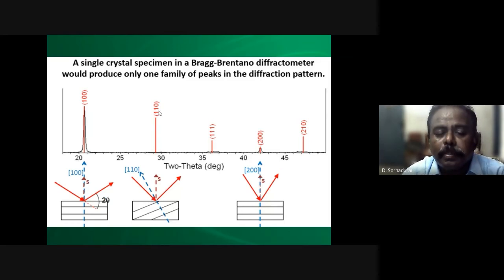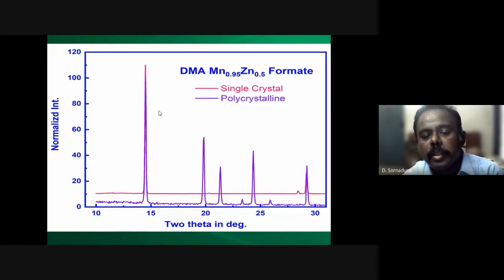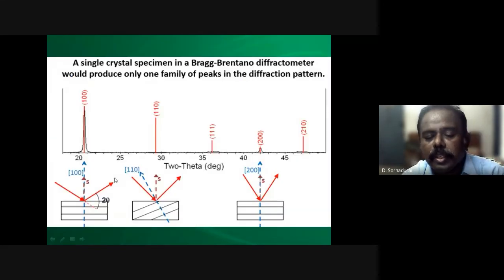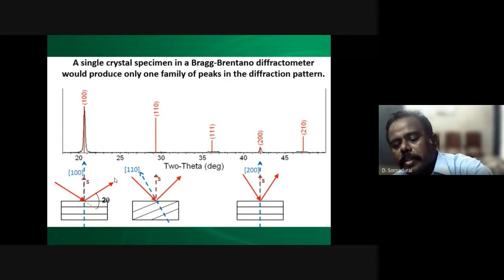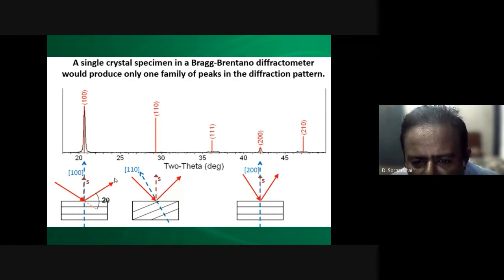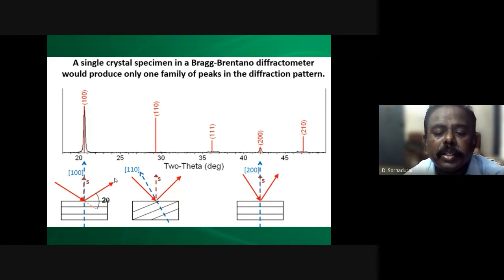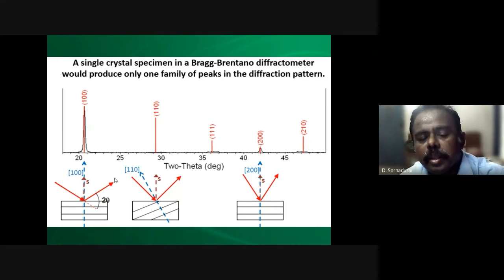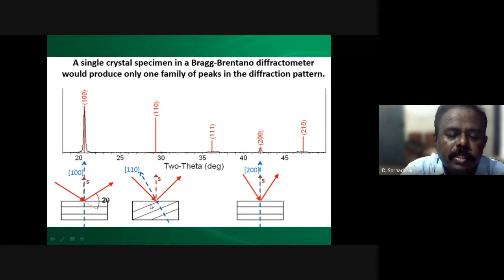As I told in the previous case, here this peak has not appeared. This peak has not appeared. Only this peak and this peak have come. The reason is they are oriented in a different direction, whereas 100 and 200 both have the same type of orientation. That is why the 100 plane is coming and the 200 plane is coming. Whereas these 110, 111, and 210 peaks are not coming at all, because the Bragg condition is not satisfied in the case of this crystal, whereas it is satisfied in the case of this crystal.